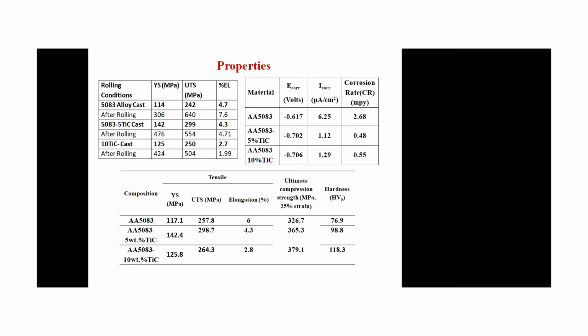and we have measured the strength in the as-cast condition and after rolling. Rolling is very easy. We can easily roll it. So you can see that after rolling, as compared to casting, where you get a yield strength of 142, after rolling it is 476, meaning a 3 times enhancement in the strength, and elongation is more or less the same. Only elongation changes.